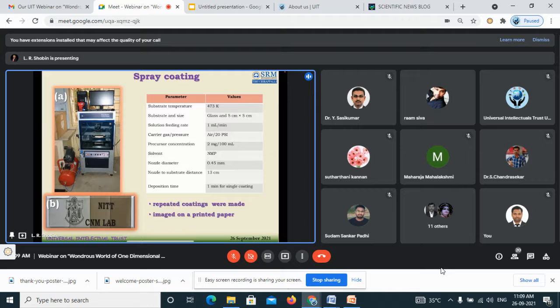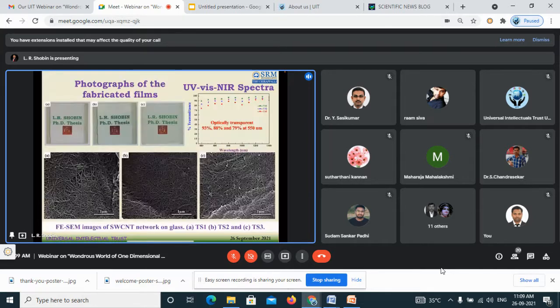So these are some of the parameters. If you see the temperature, I have gone for 200 degrees in order to dry the solvent, and the solvent is again NMP. I have to use a moderate pressure to spray this solution or the dispersion. And if you repeat the coatings, you will have different thicknesses of films. What will be the transparency?